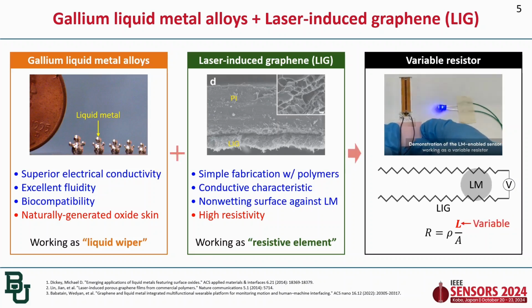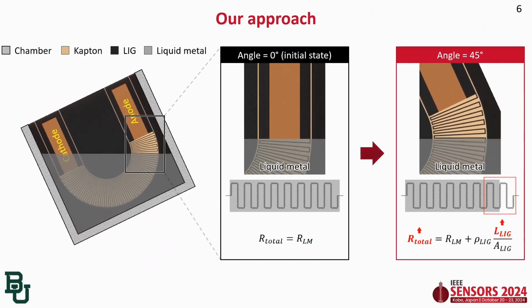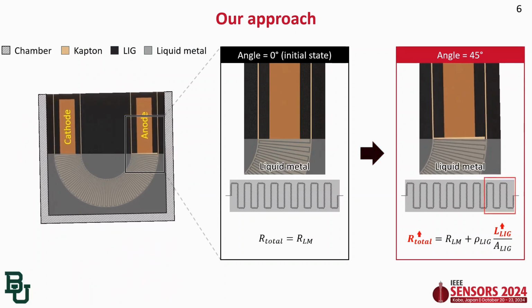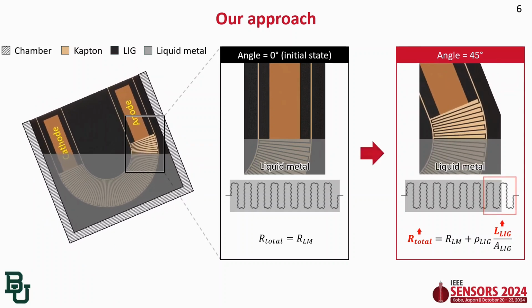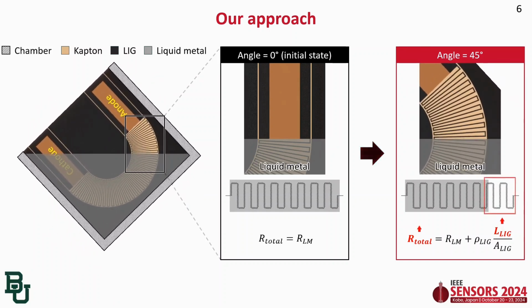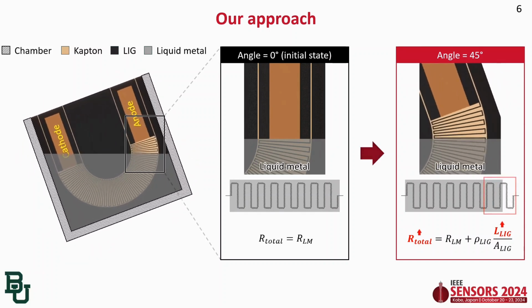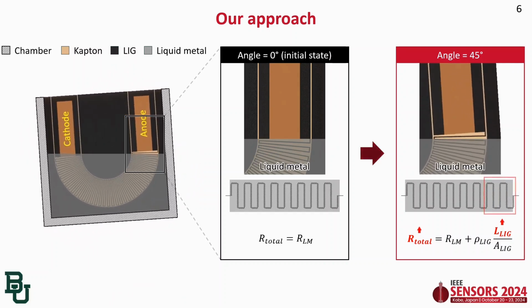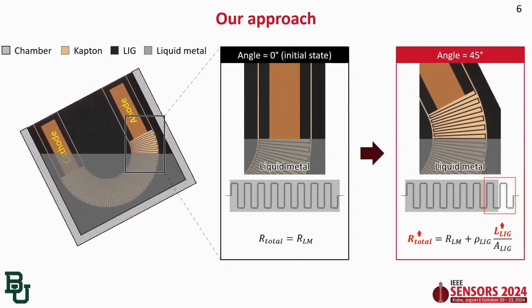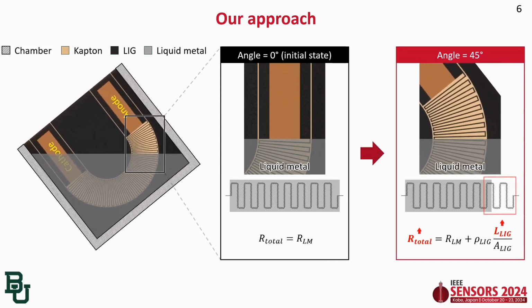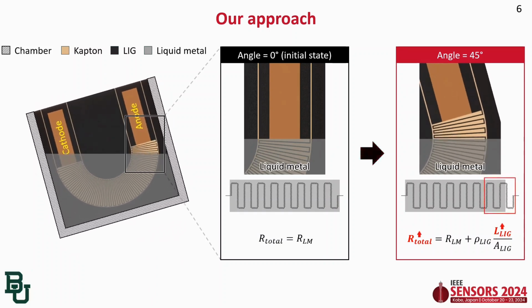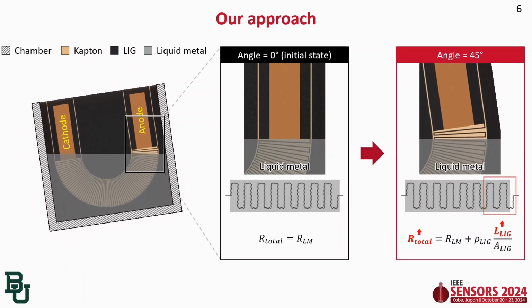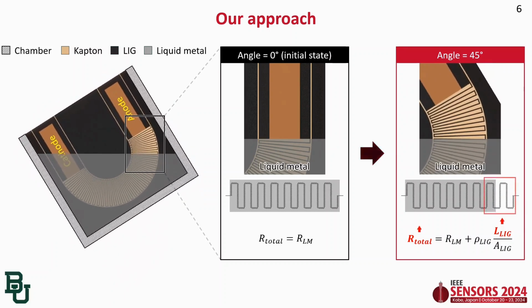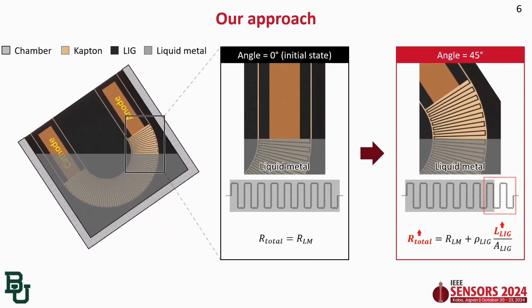Based on the resistance formula, with liquid metal droplet movement, the overall length of LIG can be increased or decreased, thus very high resistance variation can be achieved. In our approach, in a racetrack shape, a dense array of serpentine LIG electrodes can be used as the ultra-high resistive element for the tilt sensor. When the sensor is tilted, the LIG electrode emerges from the liquid metal base, creating a resistive circuit between cathode and anode. One of the important things here is having a higher length of the resistive circuit. We envisioned a resistive serpentine LIG electrode with a liquid metal pendulum as a tilt sensor. Through this mechanism, the tilt sensor can achieve ultra-high sensitivity if the length of the resistive circuit becomes remarkably long by tilting.